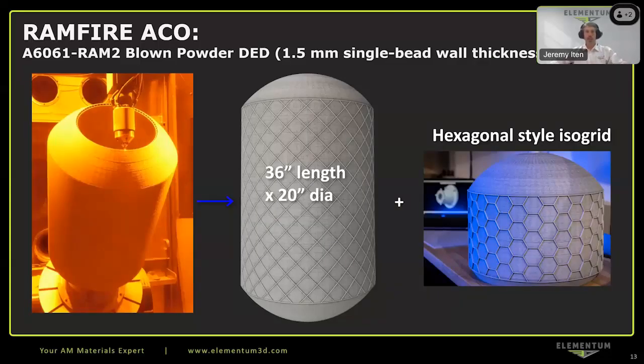So these are the cylindrical vessels that were printed using the isogrid style reinforcements. You can see on the left is an image of the printing process in progress. The printing was done with partner RPM Innovations. And so this is using a blown powder directed energy deposition process. So you're basically spraying the powder at the part and then hitting it with a laser to fuse it into the part, using a robot to control the tool pathing.